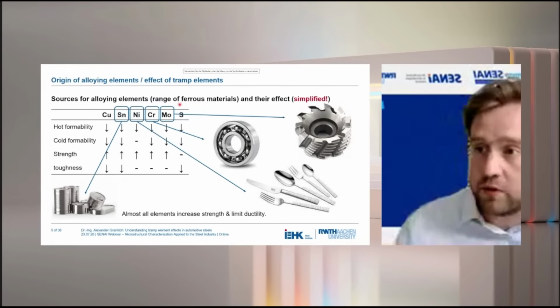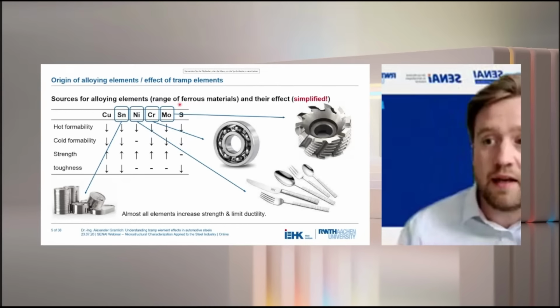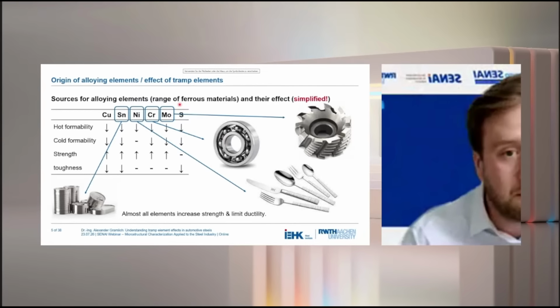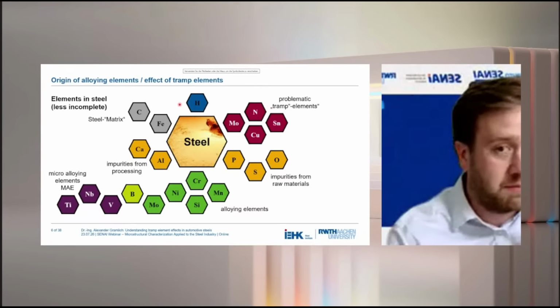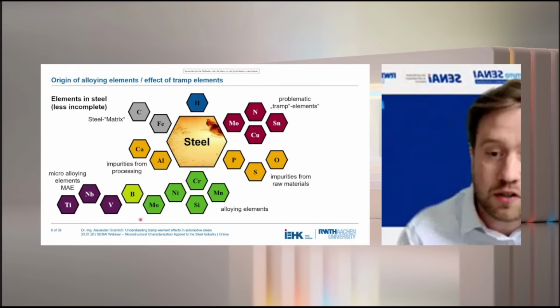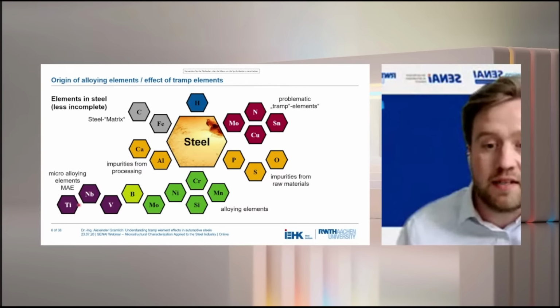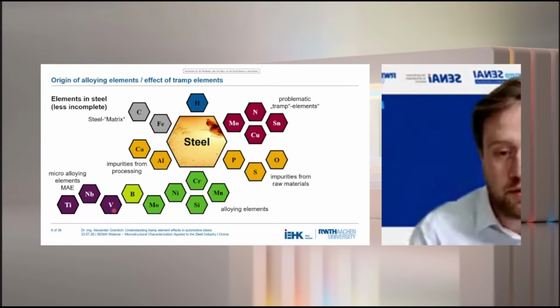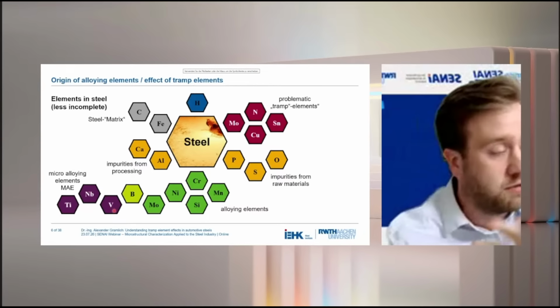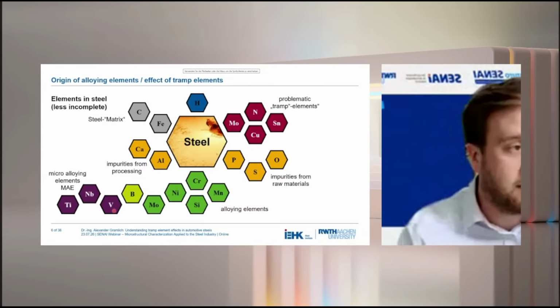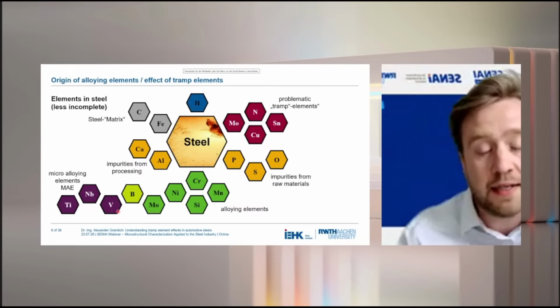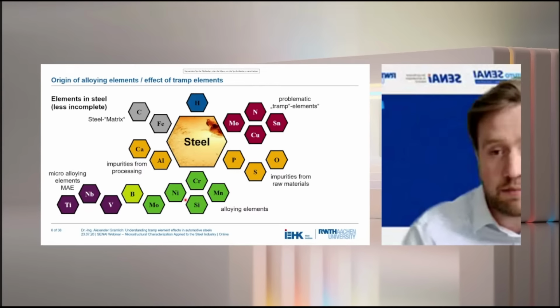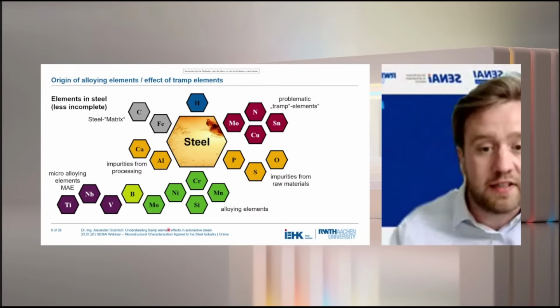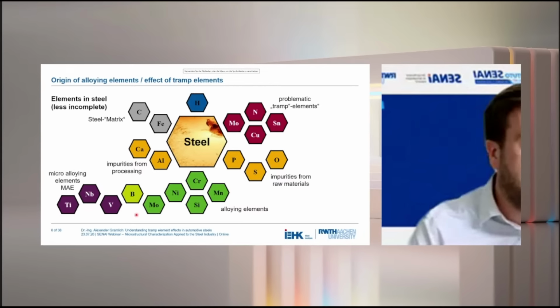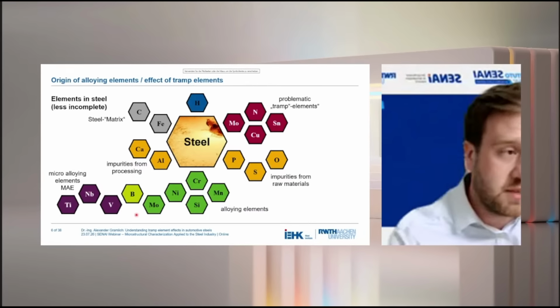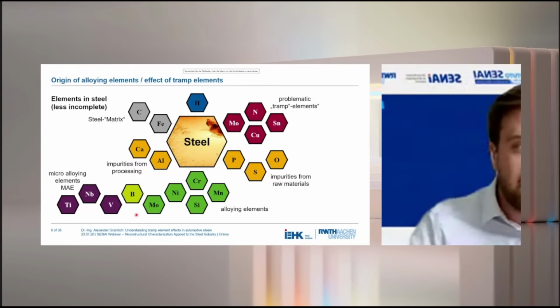I already showed you an overview of the alloying elements in steels. I gave a small note at the top that this was, of course, incomplete, but I want to also give you another example, which is a bit less incomplete, because, of course, we also have microalloying elements, titanium, niobium, and vanadium, also nicely introduced by Anderson in the previous talk. What they can do is grain refinement and other very interesting things in more advanced steels. And also boron is alloyed, for example, in press hardening steels for automotive. And all of these alloying elements are very, very dependent on the nitrogen concentration because they have a high affinity to nitrogen.